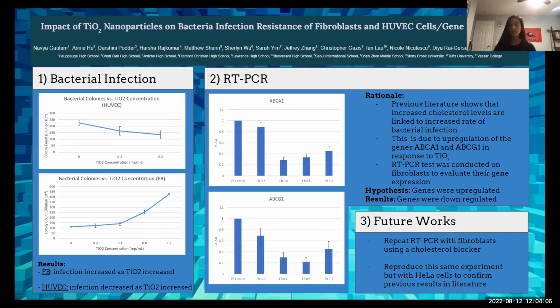So we quantified the infection for both HUVEC and fibroblast cells through increasing concentrations of TiO2, which you can see on the x-axis of these graphs. To quantify infection, we made colony counts from bacteria collected from the infected cells. And the trend for the fibroblast cells is that as TiO2 concentration increases, relative bacterial infection appears to increase as well. But for the HUVEC cells, we see the opposite trend.